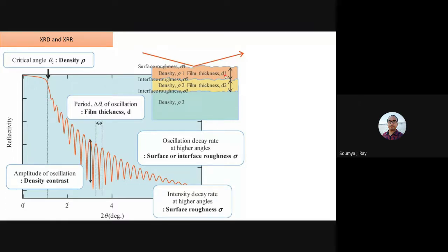You can imagine that this is reciprocal space. If you have a thickness d1, then there will be some 2 pi over d1 that will give you these kinds of oscillations. If you have a thick layer, your oscillations will be much faster, so the period will be much smaller. However, if you have a thin film, then the periodicity will be slightly larger. If you have more than one layer, one very thin and the other very thick, you can get oscillations corresponding to both layers, by having two different periods. For example, the faster oscillation will correspond to the thick layer, and a slower oscillation will correspond to the thin layer.